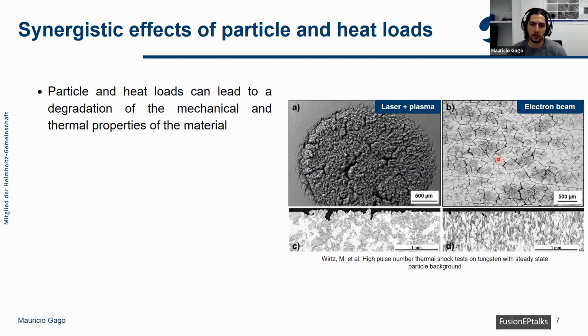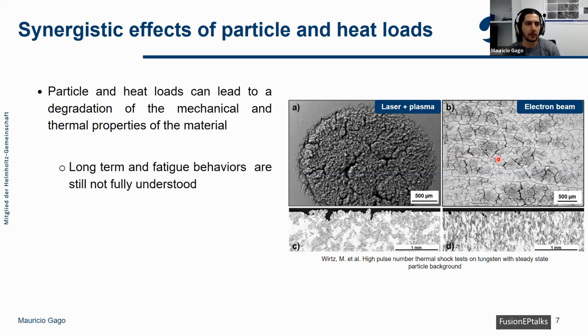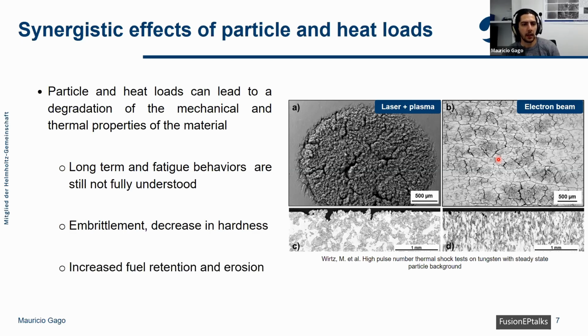So what we do know now is that these loads can lead to a degradation of the mechanical and thermal properties of the material, but the long-term fatigue behaviors are still not fully understood. They lead to embrittlement, to a decrease in hardness, or an increase in hardness, as we will see actually, depending on the area that is analyzed. And they can also increase fuel retention and erosion of the material, which is undesirable.